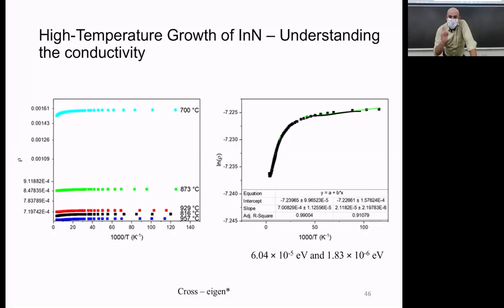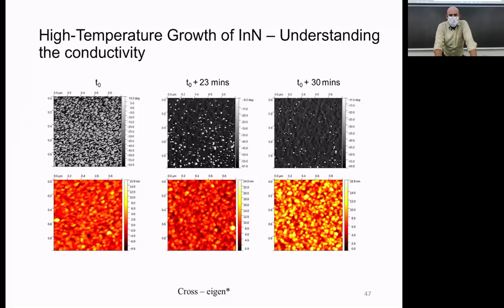And black on black was a bad choice. Don't do that. But by finding those 2 lines, it gives me gobbledygook. I'm getting excitation energies of 10 to the minus 5 and 10 to the minus 6 eV, which means virtually nothing. If I blow on them, that's enough energy to move them around. And that wasn't helpful either. So what's going on?